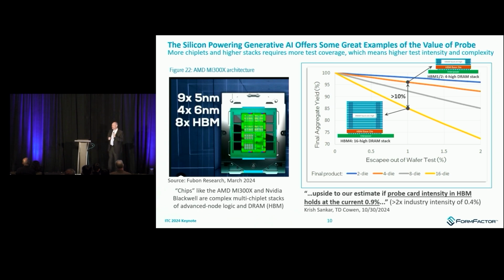Remember, I asked you to think about this 0.4% probe card spending intensity industry-wide. There was a recent report from TD Cowen, another investment bank, because they're acutely interested in understanding the entire artificial intelligence supply chain. They recently published that for HBM, probe card intensity is 0.9%. And as one of the key suppliers in HBM probe cards, that number's about right, pretty consistent with our estimates. That's double the industry-wide trend, right? Even with the climb up we saw to 0.4%, customers are spending almost twice as much on HBM probe as they do on anything else in the broader industry probe. So there's another example of how advanced packaging is driving this increase in test intensity.